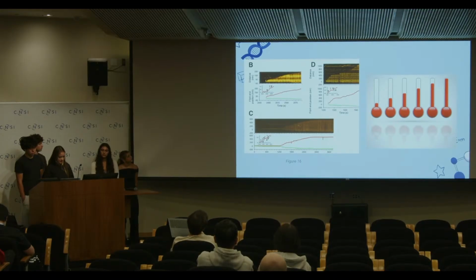So with this kymograph and the high-speed AFM, we could see the spiral shape. This is the spiral type up here, which means more coiled, that's lighter colored. Down here we can see the straight kind, and then this is hybrid, where it's a combination of the more flat and the higher. The spiral fibrils spread more easily, which can speed up the progression of the disease. The straight fibrils can accumulate and persist longer in the brain, which can cause long-term damage. And the hybrid can be highly toxic and resistant to treatment, which is especially dangerous.